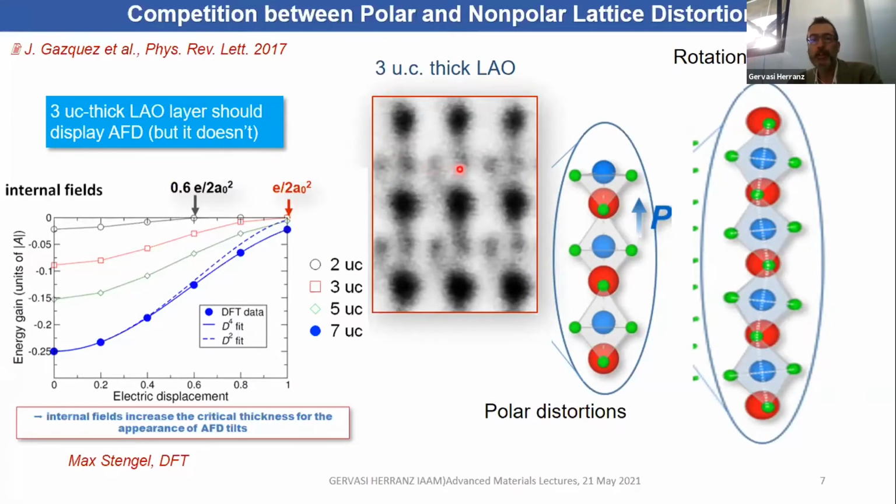And by doing this, we could establish whether there was off-centering of the ionic positions, giving rise to polarization of the lattice. But also, we could track down the possibility that the octahedral structural units, which are characteristic of the perovskite unit cell, can show tilting patterns, schematically here. And we can extract this information from these maps.